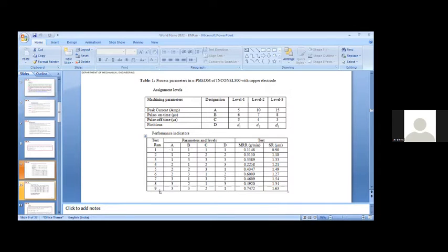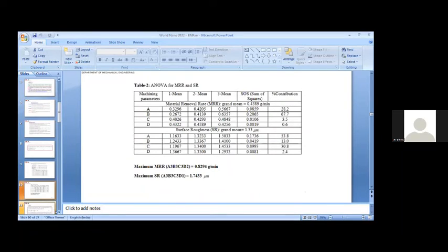From these levels, we will find the ANOVA, analysis of variation. For material removal rate, the first mean, second mean, third mean, and their percentage of contribution on the average value are estimated. By knowing this, we can find the optimum. For example, in material removal rate, you want to find the maximum value. See from the first, second, third mean, which is the maximum. The third mean is the maximum, so for parameter A, level 3 is maximum. That is why A3. Similarly, B3 is coming, C3 is coming, and D is coming as D2, the second one being the maximum. If you consider these parameters, you can achieve the maximum material removal rate. In the same way, for surface roughness you see the minimum values. This way, it is possible to find the optimum values.